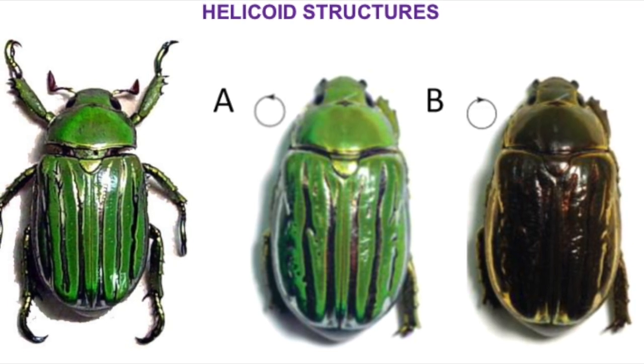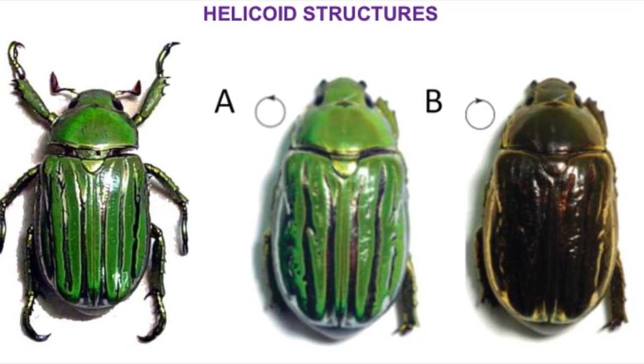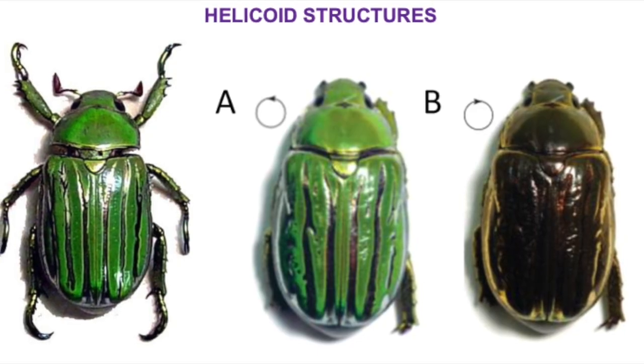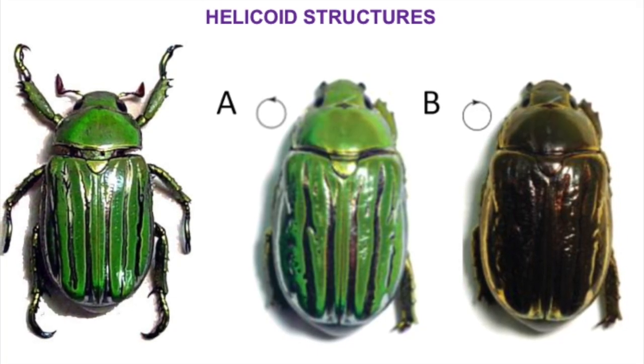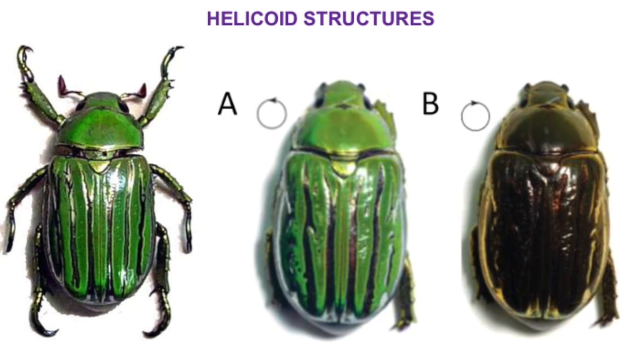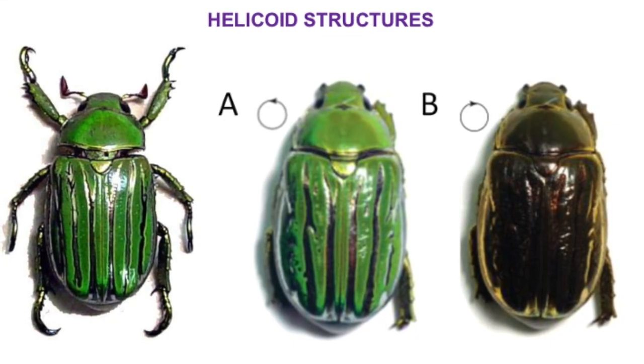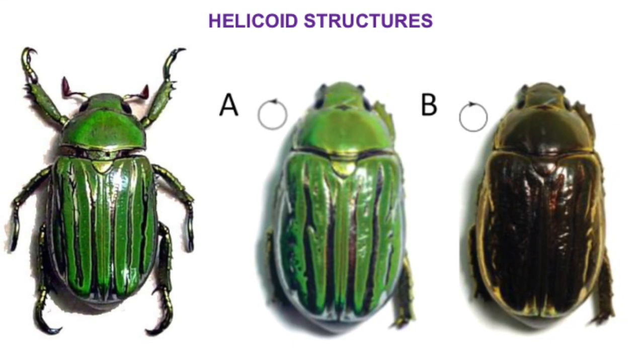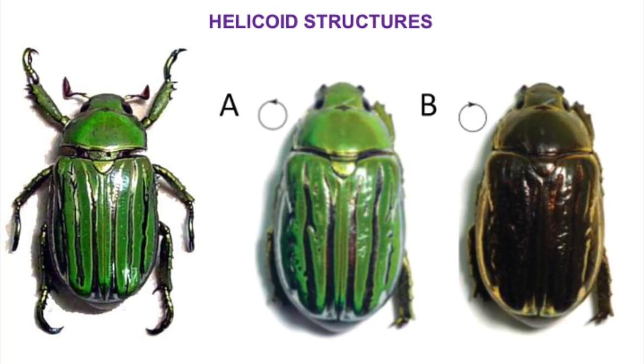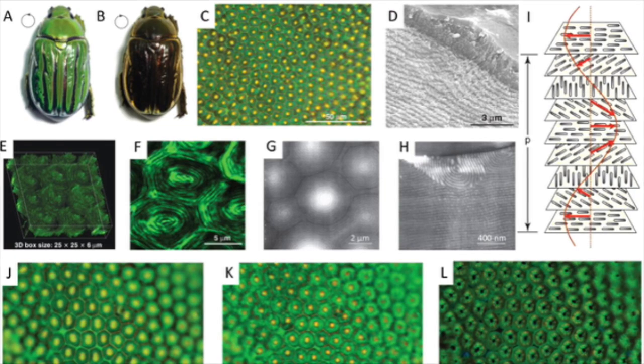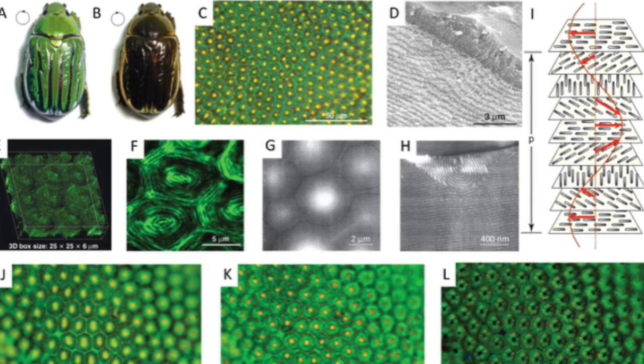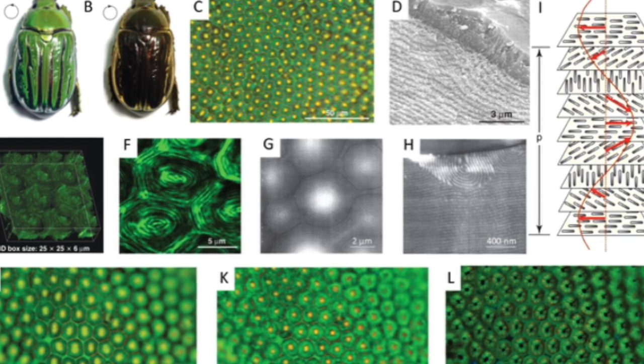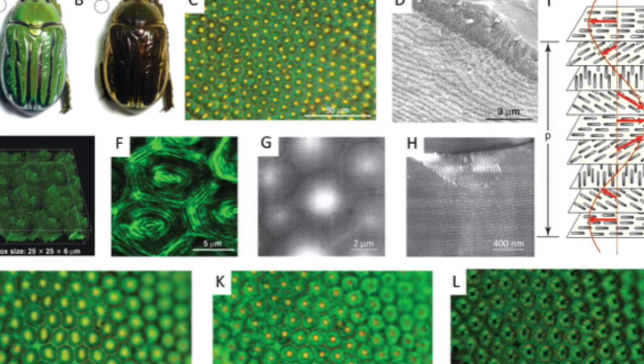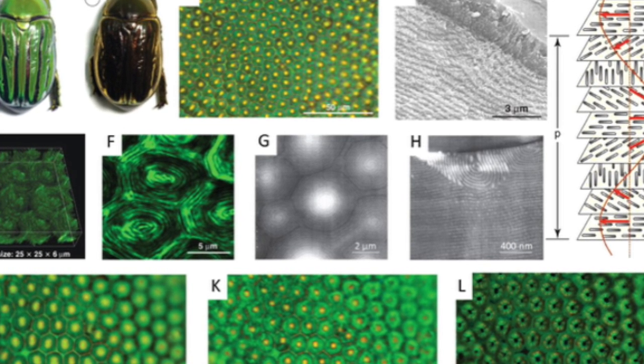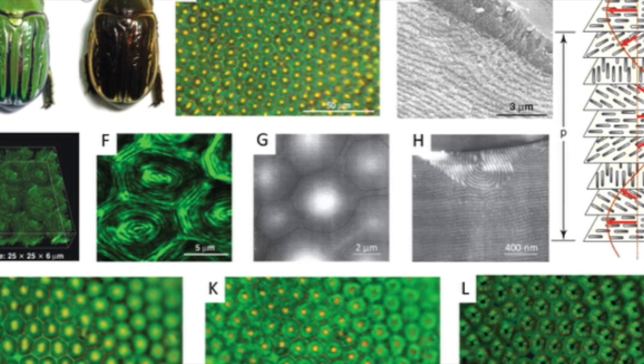A prominent example is the exocuticle of the beetle Chrysina gloriosa, which selectively reflects left circularly polarized light and therefore exhibits a brilliant metallic appearance. When left circularly polarized light is removed from the incident illumination using a quarter-wave plate and a polarizer, the beetle's characteristic bright green reflection disappears. This selective reflection of circularly polarized light originates from nanoscale helicoidal features in the exoskeleton, whose periodicity is comparable to the wavelength of visible light.